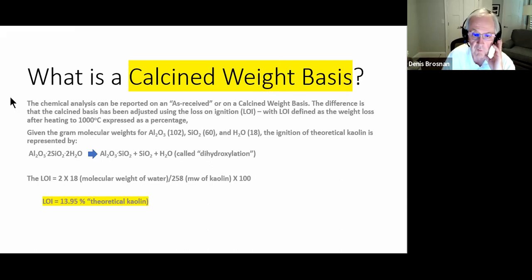Now, here's another reinforcement. We already talked about a calcine weight basis, but you can see if kaolin, given the theoretical formula, decomposes into a substance we would call metakaolin. You'll learn more about this when we start talking about sintering aluminosilicate ceramics. It will kick out a silica molecule and it'll kick out water. So you can calculate the loss on ignition of 2 times the molecular weight of water divided by the gram molecular weight of kaolinite, and that turns out to be 13.95%. And so we use that in converting between an as received weight basis and a calcine basis.